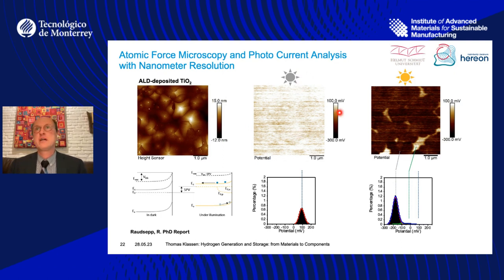There's not much contrast. If we illuminate by a laser, which is tunable, then we can see the dark areas give us a lot of potential. So here, a lot of charge carriers are produced, while in the bright areas, almost no charge carriers are present. So we can directly correlate with a height profile which areas of the specimen are good and which are bad.